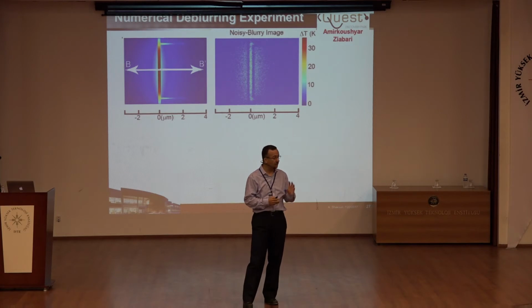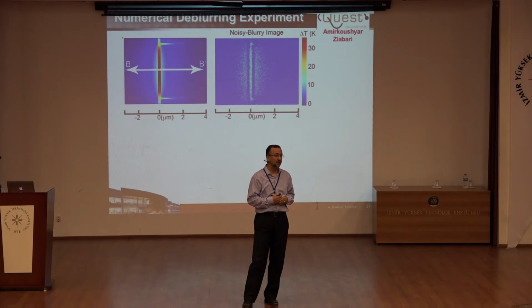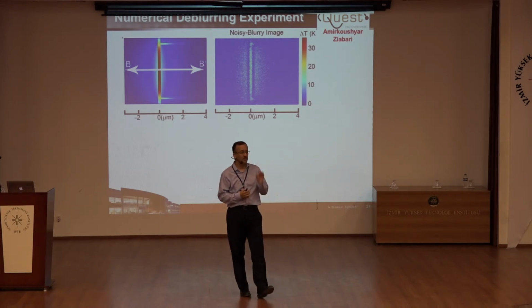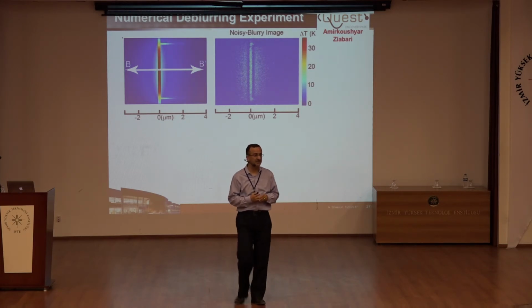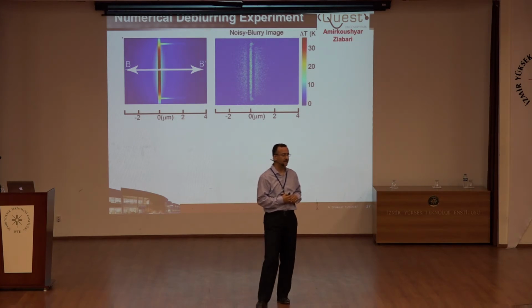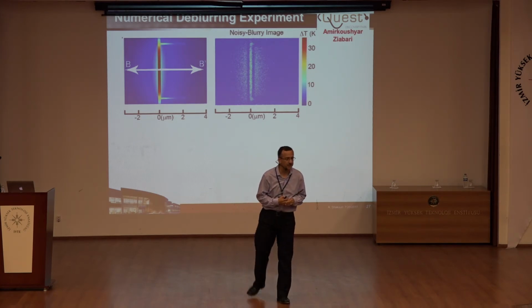If you use the inverse methodology that I described, the inverse problem is very sensitive to signal to noise. With the signal to noise that we have today, which is on the order of 20 dB, a factor of 100 for very nanoscale measurements, or a factor of 1,000 in some of the very good, clear, very smooth samples, we can go down to 100 nanometers. A 100 nanometer non-contact far field measurement is the best result we have shown.